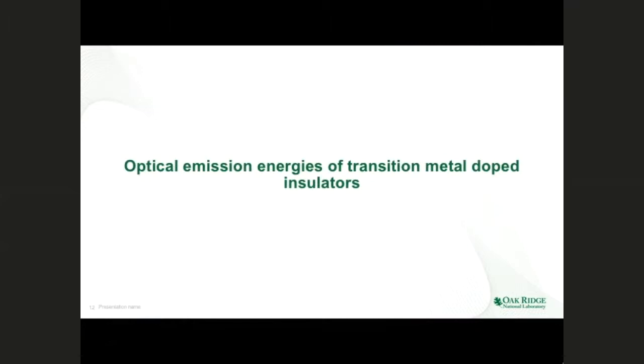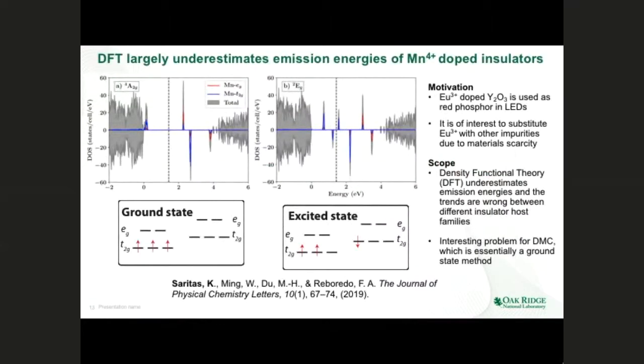So with that, I want to come to more of a nanoscale understanding of the material. What we are going to discuss here is the optical emission energies of transition metal doped insulators. And now we actually come to the area where we really need to use very large simulation cells. We are working with manganese 4+ doping, and we need to take into consideration dopant-dopant interactions to make sure that we are using simulation cells that are large enough. The basic idea from the materials perspective is to replace the europium 3+ doping in LED materials with a manganese 4+ dopant, since we know that manganese is much less scarce than europium, and it will be of interest for materials applications.